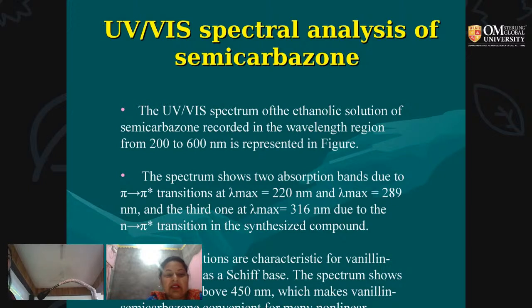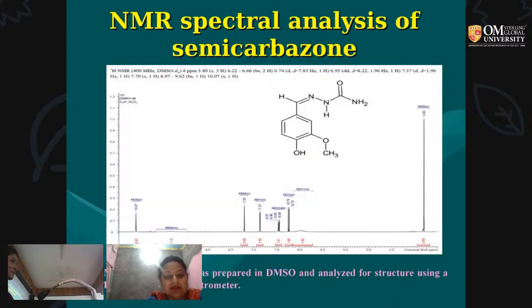The third one, at lambda max equal to 316 nanometer, is due to n to pi star transition in the synthesized compound. These transitions are characteristic for vanillin semicarbazone as a Schiff base. The spectrum shows no transition above 450 nanometer, which makes vanillin semicarbazone convenient for many non-linear optical applications.